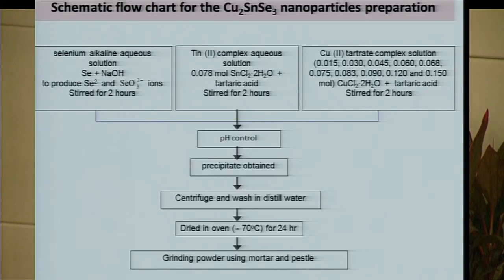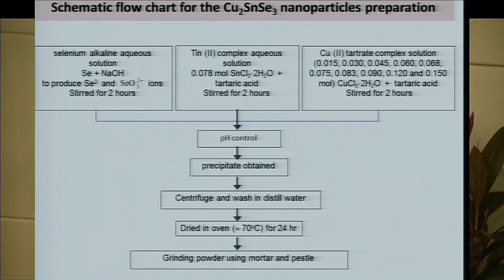As we understand the process, we are bold enough then to try to synthesize a ternary compound. And to synthesize a ternary compound is basically not that easy, but it's not that difficult also. What we did was to fix the concentration of the selenium and fix the concentration of one of the metal ions and vary the other types of metal ions. And then we look at the kind of reaction that was going on.